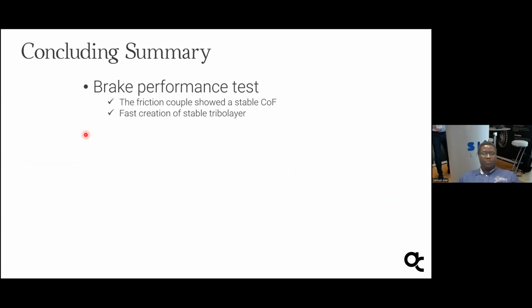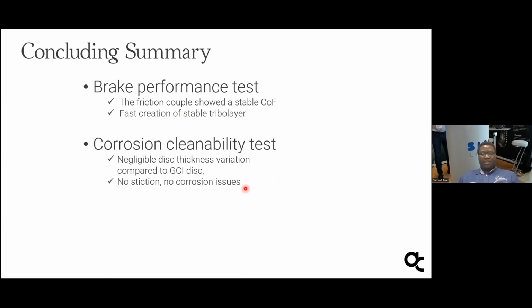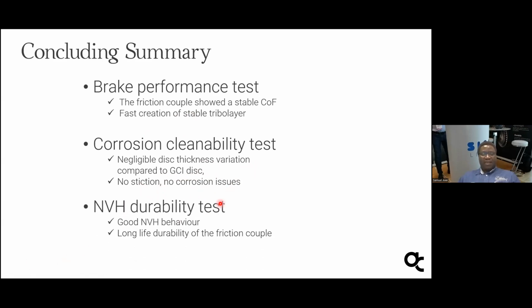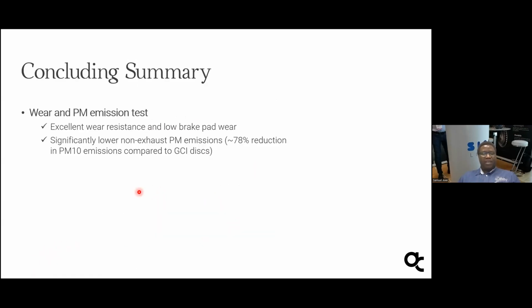And in conclusion, from the brake performance evaluation, the friction couple shows a stable coefficient of friction, fast creation of a stable tribological layer, and in the corrosion cleanability test, we have a negligible disc thickness variation compared to the GCI disc, no stiction, no corrosion issue. For the NVH durability test, there is good NVH behavior and long life durability of the friction couple. Also in the wear and PM emission test, excellent wear resistance and low brake pad wear, significantly lower non-exhaust PM emission. It was approximately 78% reduction of PM10 emission compared to that of the GCI.